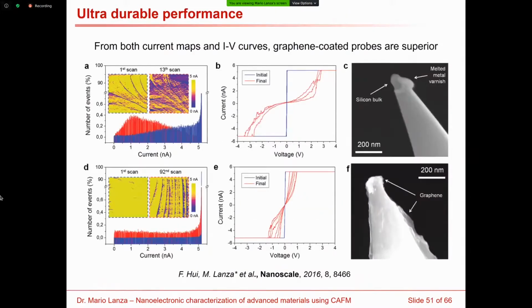So we compare the standard tips with the graphene-coated tips, and you can see that for the graphene-coated tips, we achieve a much longer lifetime. And with the same type of tip, just putting graphene on top with this very easy method, we can scan 92 times with the same condition. And the decrease in the conductivity is much, much lower. So basically, this is demonstrating that there is a much larger lifetime.